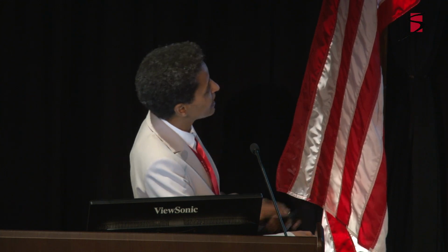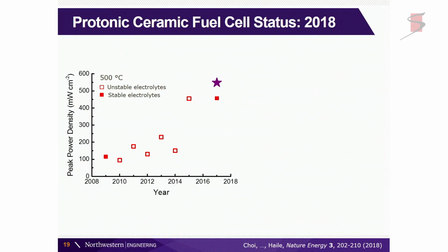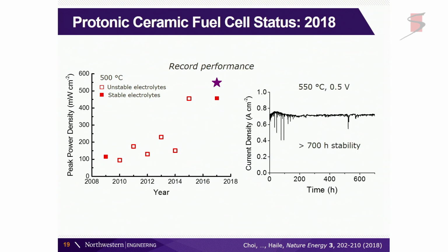Okay, so let me now show you then in 2018, a couple of other nice results had come out, but here's our fuel cell, and we're using a stable electrolyte, so that's been a lot of fun. So that's our record performance there. And then we also, of course, measured stability, and it lasts for a very long time. And that's important because we have that 100 nanometer thin layer, so we wanted to ensure that that was nice and stable as well. Okay, so now we're doing better than the oxygen ion conductors are doing.